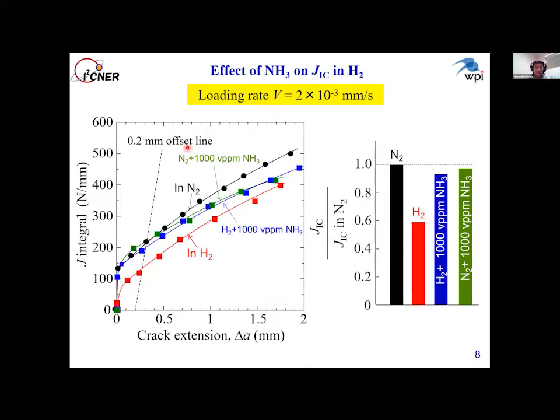So this is a result of the fracture toughness test with a higher loading rate. The explanation of the graph is a little complicated within limited time, so I'd like to explain the result based on the J1C fracture toughness value. So please look at this bar graph. In hydrogen, the fracture toughness value was significantly reduced. In other words, hydrogen embrittlement occurred.